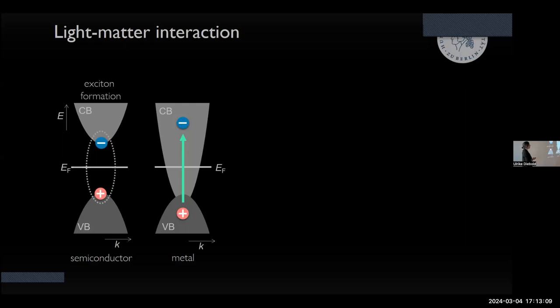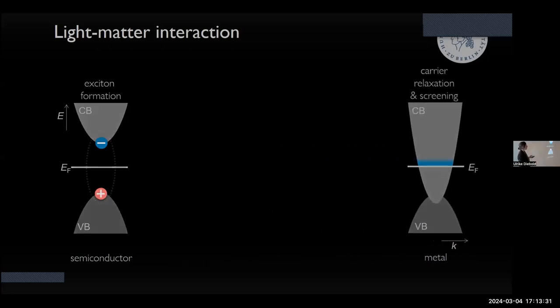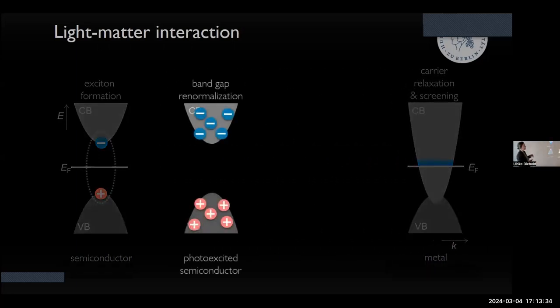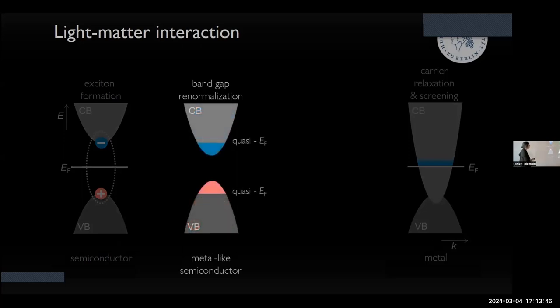In metals, the situation is different. We also have the attractive Coulomb interaction that leads to exciton formation, but it is screened because we have free carriers at the Fermi energy, and they contribute to the screening, and so we can monitor the single electron dynamics in a metal. Then we can create metal-like properties in a semiconductor simply by exciting it sufficiently strongly. This is well known. You generate many carriers in both bands, and then these form quasi-Fermi energies in both bands where you have free carriers.